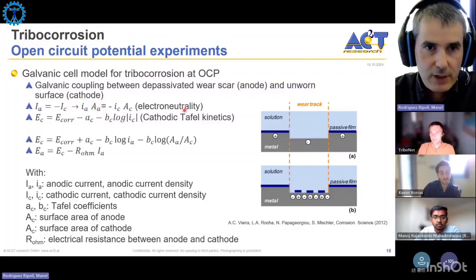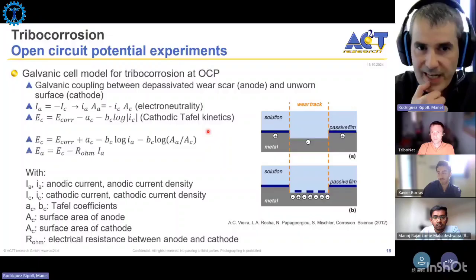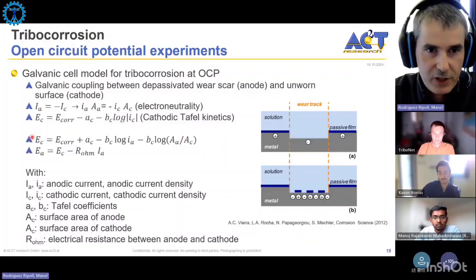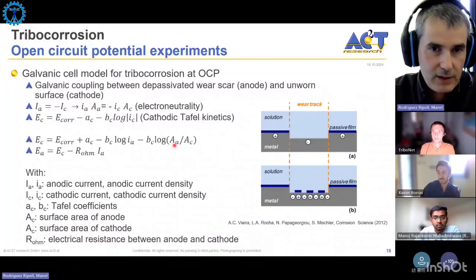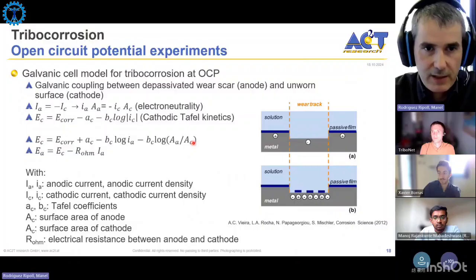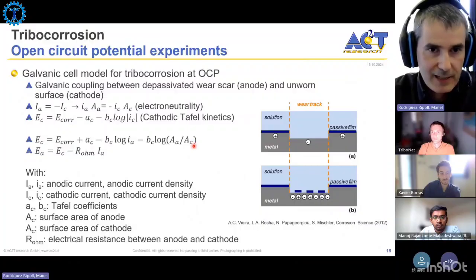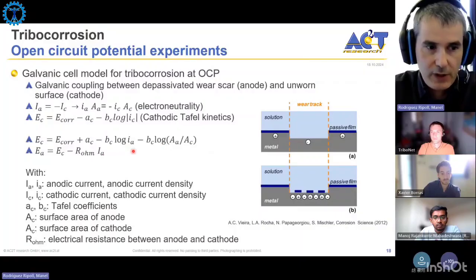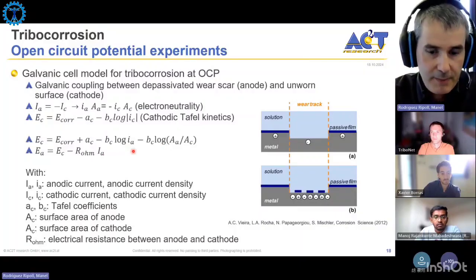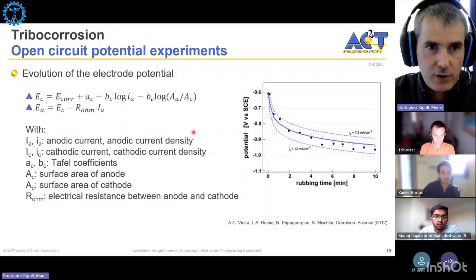And if you assume this electroneutrality and the Tafel kinetics that we talked about before, these slopes of the anodic and cathodic branches, you can end up with an equation like this, where you know your anodic area, which is basically the worn area, and the cathodic area, which is the area outside the wear track. You have these Tafel coefficients that you can get experimentally from the slopes, and by knowing all of this, you can correlate, for example, the cathodic potential. If you know the corrosion potential, you can see how the cathodic potential evolves with time.